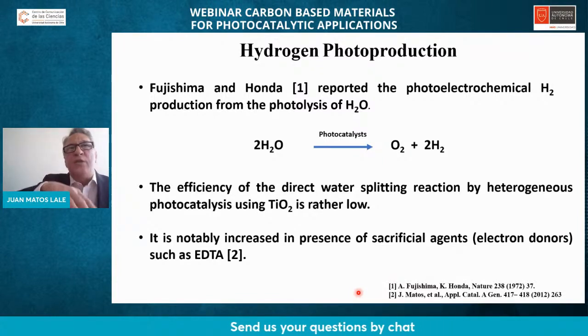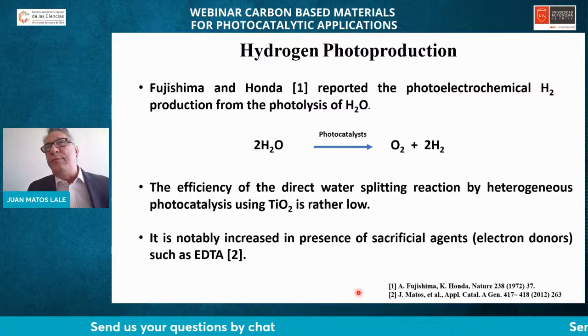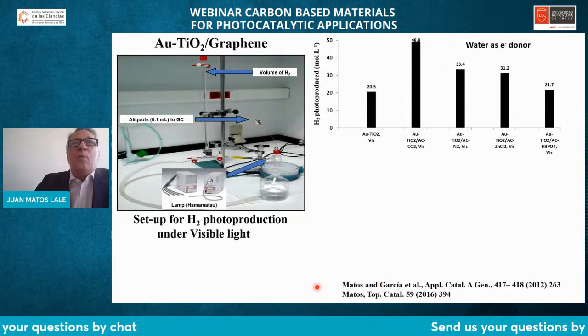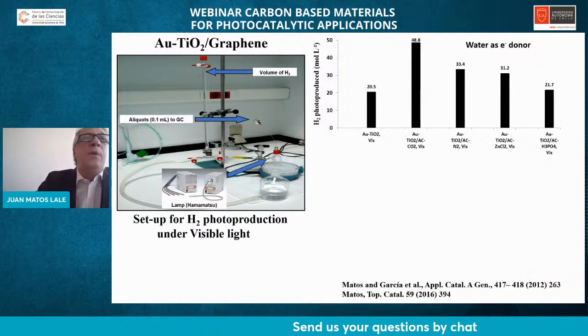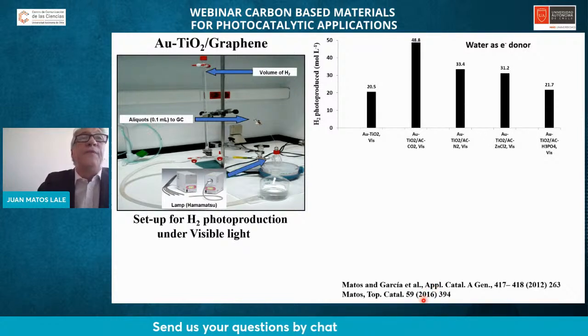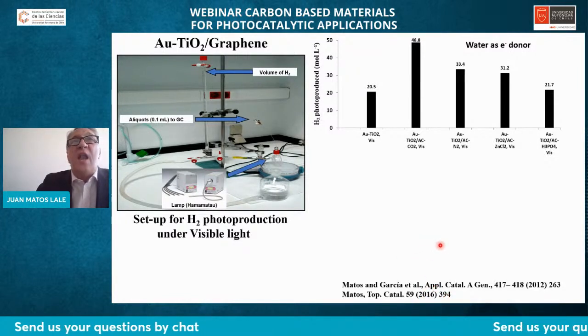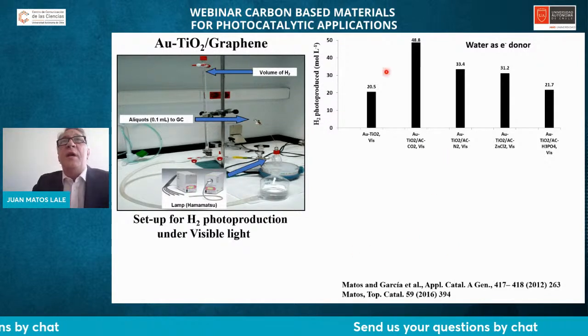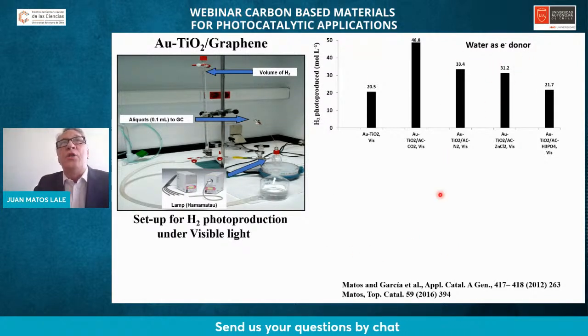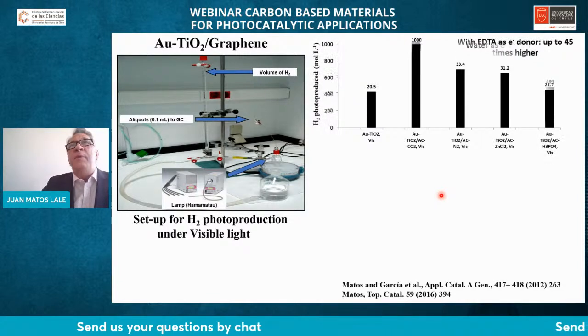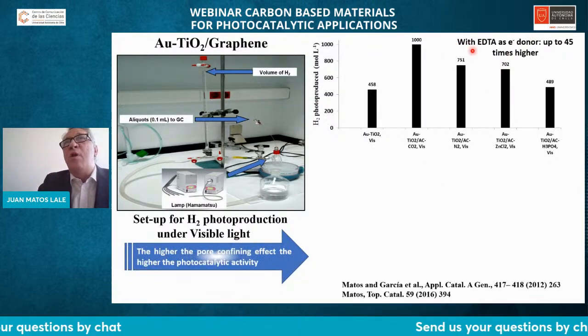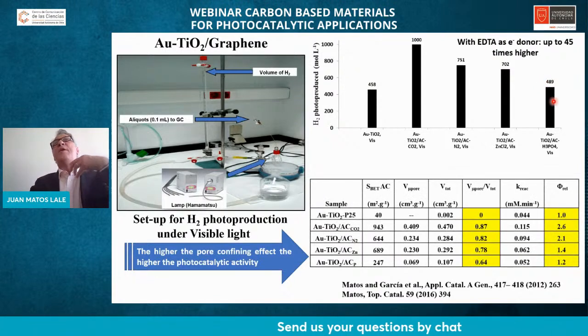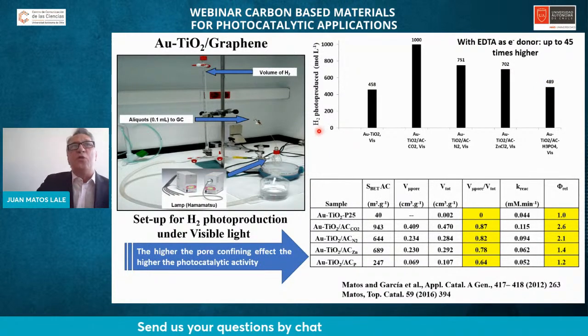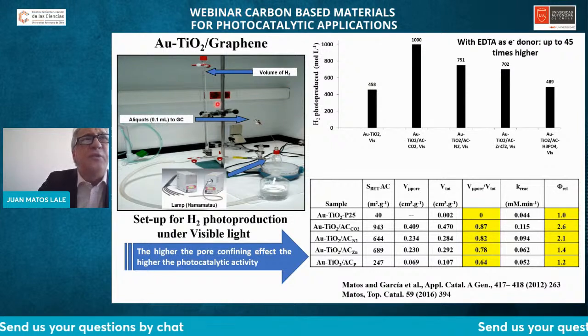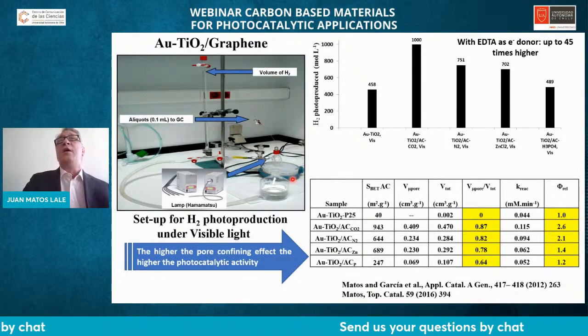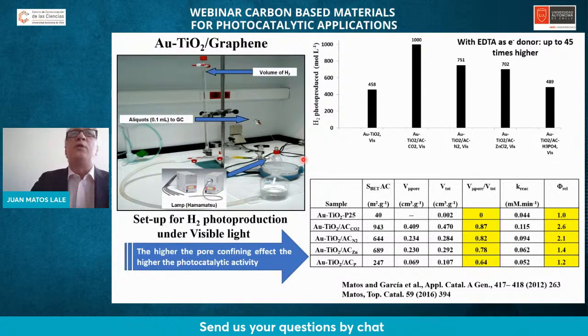So this reaction has been gaining attention in the last 10, 15 years. For example, we published 10 years ago with Hermenegildo Garcia from the Institute of Chemical Technology in Valencia, Spain. We reported the difference between water as an electron donor in comparison with ethylenediaminetetraacetate. When we employ this molecule as an electron donor, we are able to increase hydrogen production by a factor of 45 with a very simple photoreactor, very simple. When you don't have too much money to start a laboratory, you need to be creative.